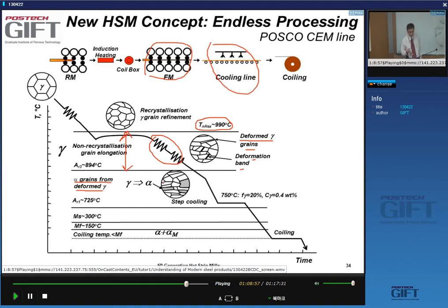And as a consequence, you get a refinement of the microstructure. In the cooling line, you can play around with the transformations so that, for instance, you have a stepped cooling, and you can then make a more interesting microstructure. In this particular case, and we'll talk about this in the next lectures, we try to make what's called a dual phase steel. A dual phase steel, and so we use a stepped cooling.